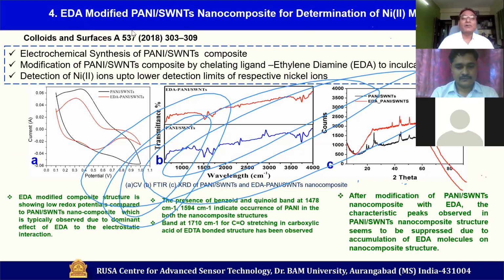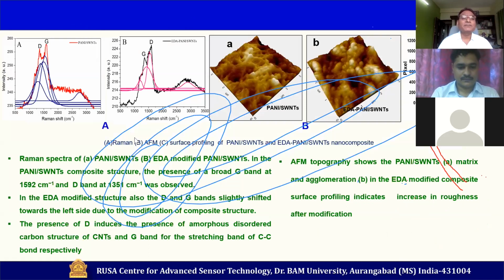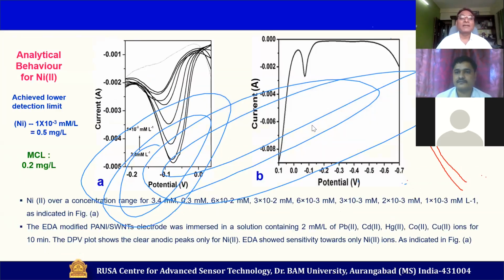So we went ahead and modified polyaniline SWNT substrate composite with EDA, and you can see we got wonderful results. This is just a confirmation for CV, and then this is FTIR and XRD, the clear-cut discrimination between bare and modified and composite. And then you can see this is Raman spectra as well. This is Pani SWNT, and this is EDA modified Pani SWNT. There is clear-cut distinction. As far as AFM is concerned, you can see after modification there is a substantial increase in roughness level. You can see this is from the AFM image, and the roughness profile. So through this profile, you can easily conclude that yes, the surface roughness increases because of the chelating ligands, and this is what we were expecting.